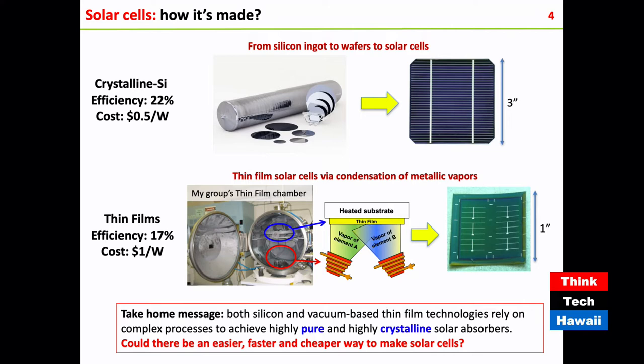Right. And the method that we use in my lab and also in other labs to make thin films is to use what we call a vacuum chamber. Mm-hmm. So what you see on the bottom left is the actual vacuum chamber that we use in my lab. At the very bottom, you have crucibles that you can heat up, and you put metals in these crucibles. And on the top part, you have the substrate. And by sublimating, heating up these metals with the crucibles, you form a vapor of elements that eventually condenses on the substrate. Okay. And so you can control the thickness of the film, the temperature, and grow thin films or cells this way.